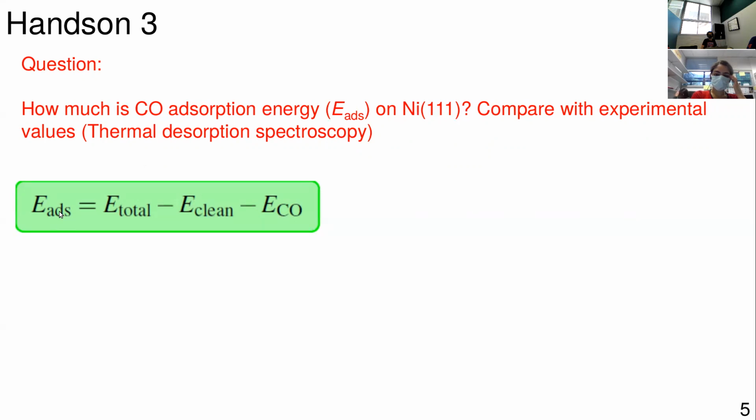Okay, did we have any comparison with experimental values? I found one which is near, that is 0.31, but after that I have seen that the coverage is not the real one, because this is with a 0.2 coverage value. Okay. As I understood from the last session of doubts, with a higher coverage, it must be a greater number, a positive number. Exactly. Yes. It should be less negative, let's say. Yes. Should be less stable with a higher coverage.